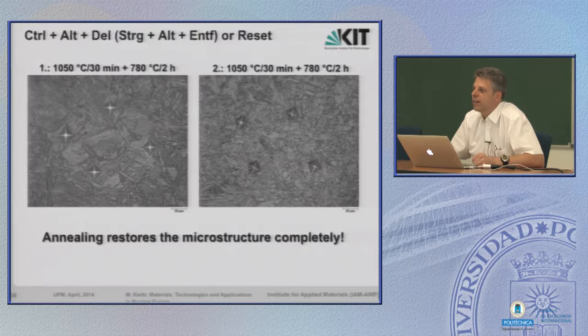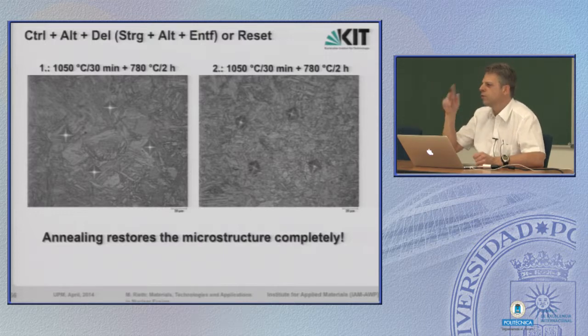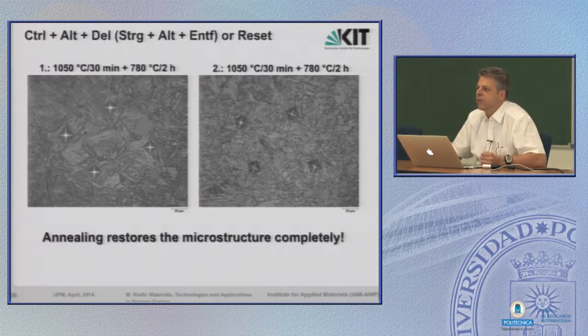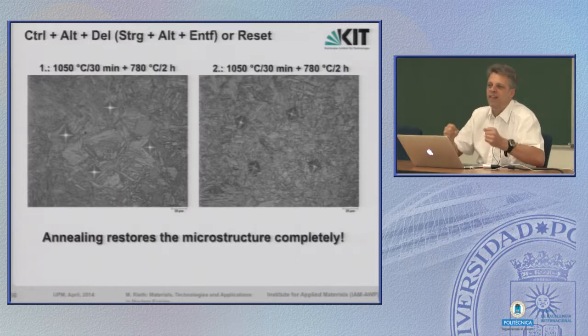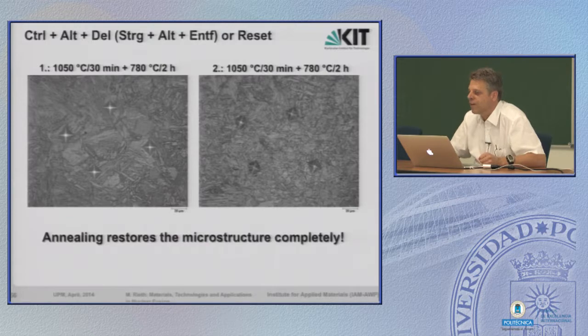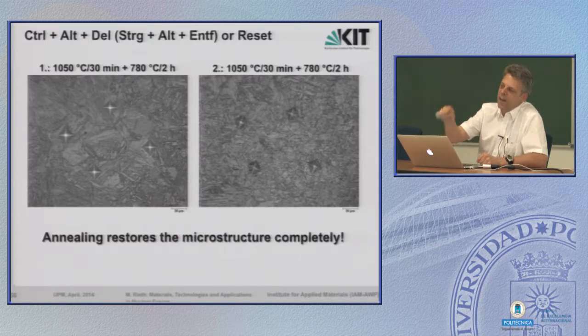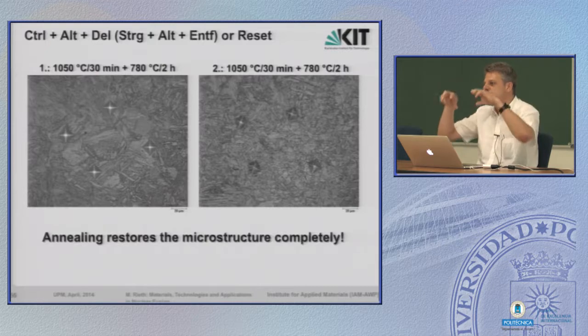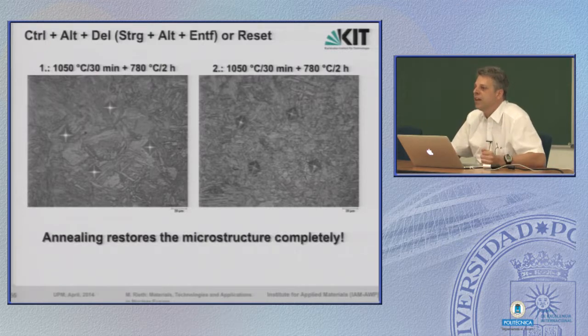And this you can do at any time. We have done this 20, 40, 50 times. Whatever you do with the material, you can destroy it, for example, by welding, bending, cold working, or whatever measure. If you perform this treatment again, this means you push the reset button and the material is fully restored in terms of microstructure and properties. And this is the main difference as well as the main benefit of martensitic steels like Eurofer.